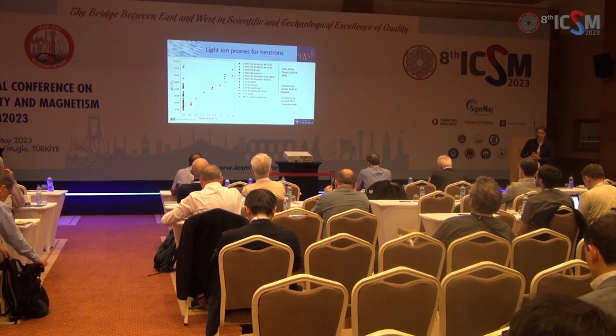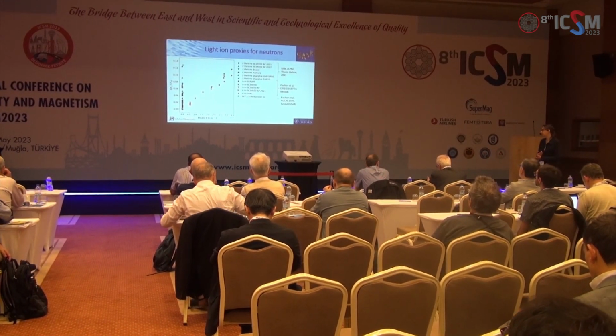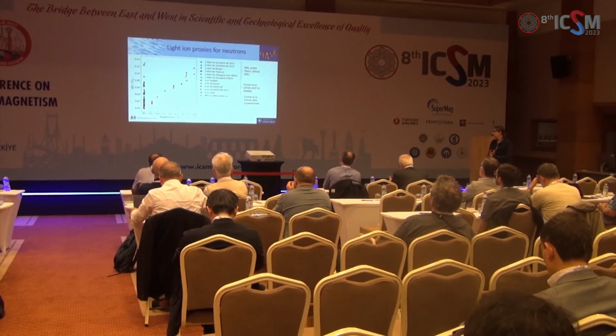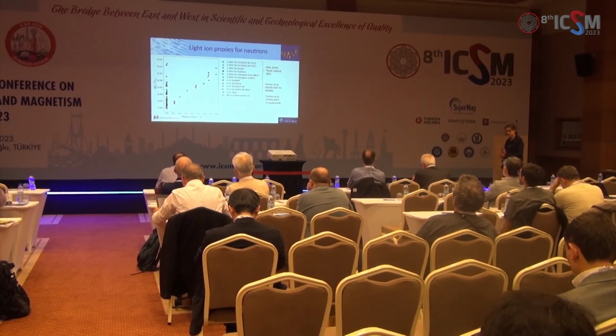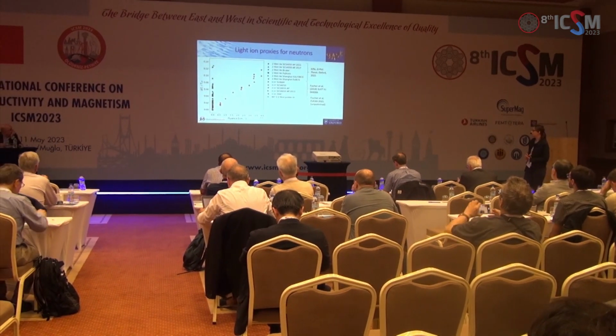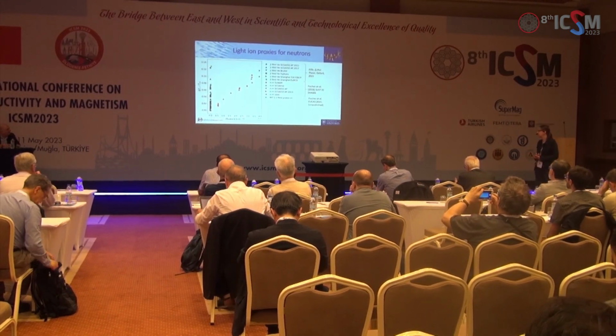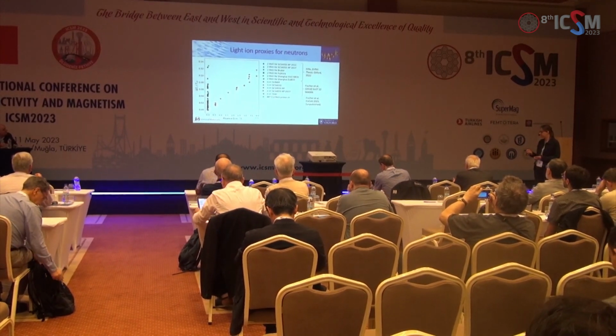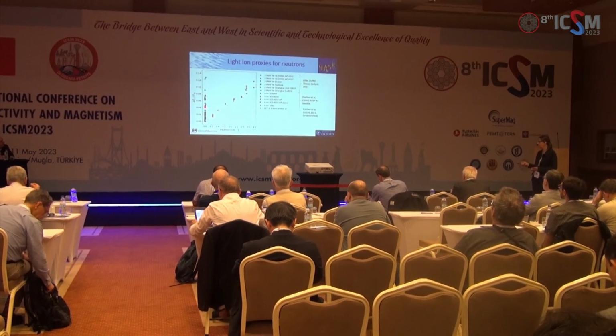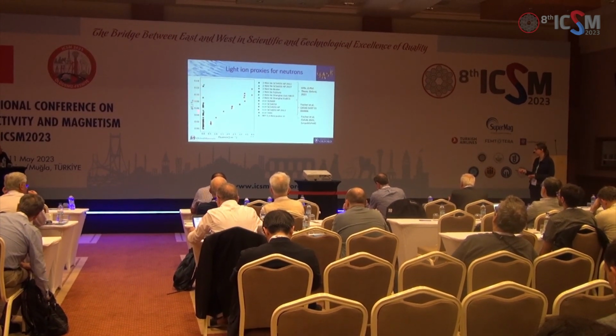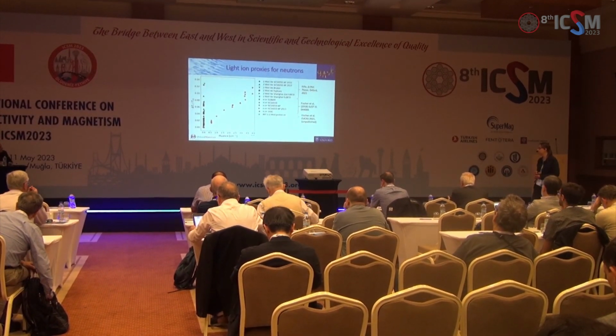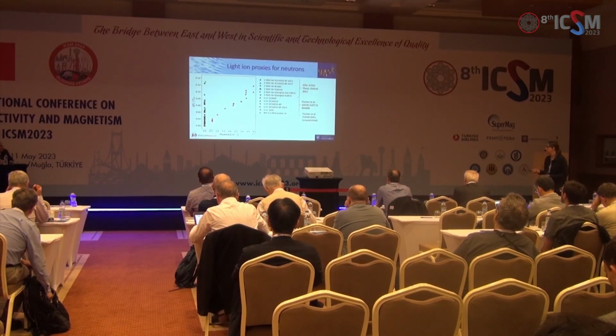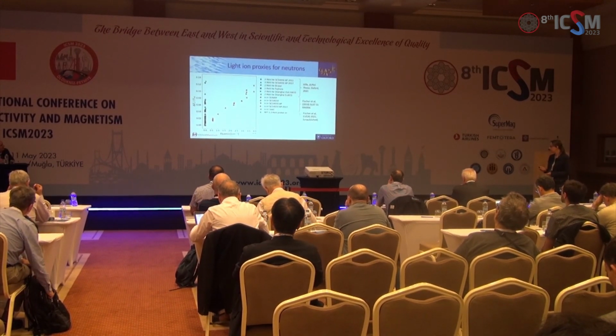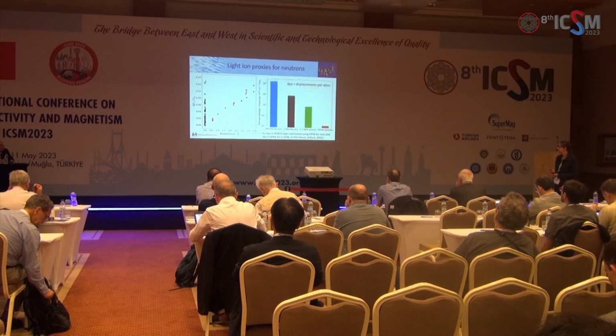So how good are light ions, for example, as a proxy for neutrons? Well, if we plot what happens to TC, or the change in TC on irradiation, as a function of fluence for different species, we find that it looks very different on this graph. So neutrons have this gradient here, and our helium ions that we've done in Oxford, a much steeper damage rate, and protons also quite steep. So what's going on here?